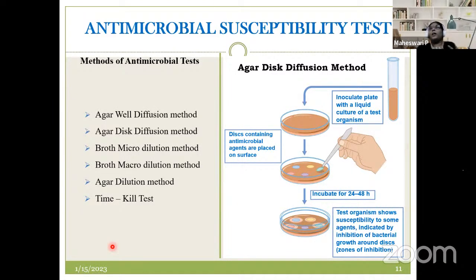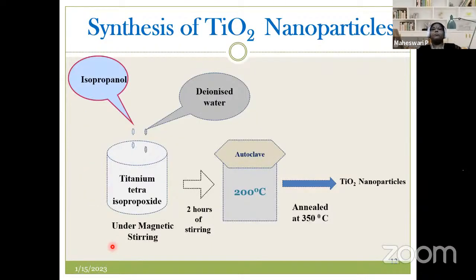Now let us go for the synthesis which we have done in our experimental part. The precursor, the main material, we have chosen is titanium tetraisopropoxide, along with deionized water and isopropanol. We mixed it for nearly 2 hours in a magnetic stirrer, and then the contents were transferred into an autoclave and maintained at 200 degrees centigrade. After that, we centrifuged it and dried it in an oven, and the powder was annealed at 350 degrees centigrade, because our target is to get the anatase form of titanium dioxide. After that, the particles which we obtained are titanium dioxide.